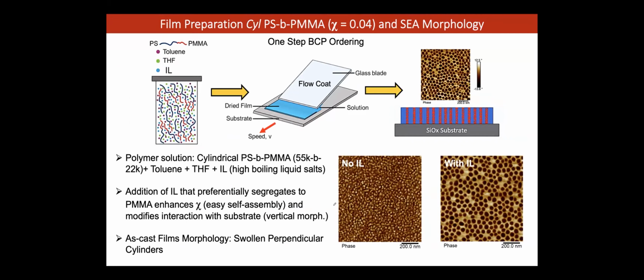The great news is that in the drying process of these block polymer films, in that short evaporation time, the ionic liquid, because it's a liquid, can readily find its way into one of the blocks, like PMMA. Down below in this picture, with no IL, you're not getting a very good structure from the as-cast film, but with IL you can have very nice domain structures. With AFM you would think the cylinder is going vertically down, and that's where GISAXS comes in to verify how far down they go, and the size, orientation, and distribution. That's the value GISAXS brings.